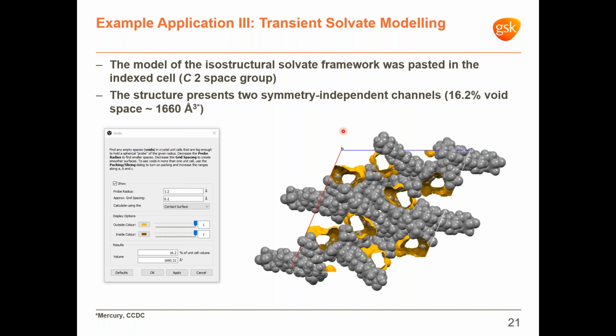In the void distribution analysis, a 16% void space was estimated by Mercury in the dry framework structure, presenting two symmetry-independent channels. And based on the 18 cubic angstroms rule, the void space could, in theory, account for the presence of up to 12 molecules of solvent in the unit cell, corresponding to the experimentally suggested 1.5 to 1 solvent to API ratio.